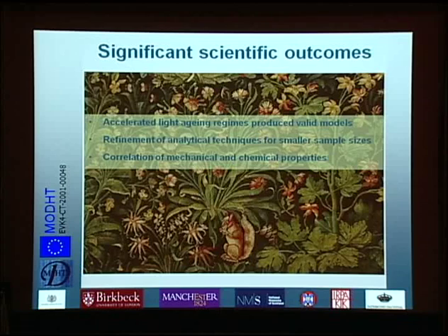And we've also shown that the accelerated light aging produces valid models, which was not clear from the outset of the project, because we took the samples from the back of the tapestries where they did not receive any light. But we've shown that what happens to them chemically is actually exactly the same.